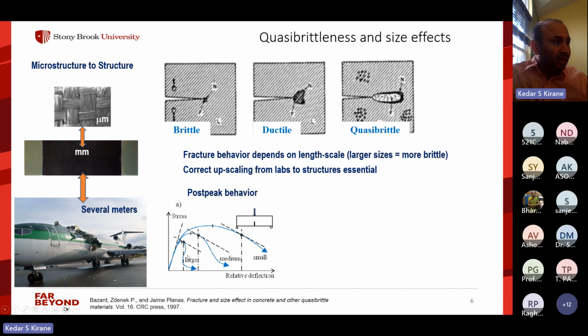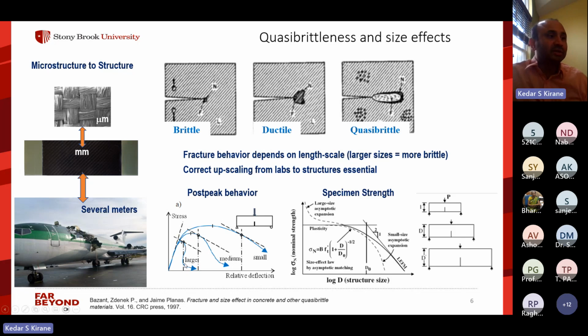Now, one of the things that happens with changing size is that the stability of the post-peak behavior changes. For example, smaller specimens are often more stable in the post-peak region, and then larger specimens become more unstable. And there is a very important concept called the size effect law, which basically says that larger structures have smaller nominal strength. Okay, this is not the material strength. Material strength is a constant, but the specimen strength, which is the total load divided by some kind of nominal area, decreases with increasing size. And now this is also the prediction of linear elastic fracture mechanics, of course. But if you consider linear elastic fracture mechanics, which applies to purely brittle failures, the scaling of strength versus the size D, plotted on log scales, will show almost a linear plot with a slope of minus half.